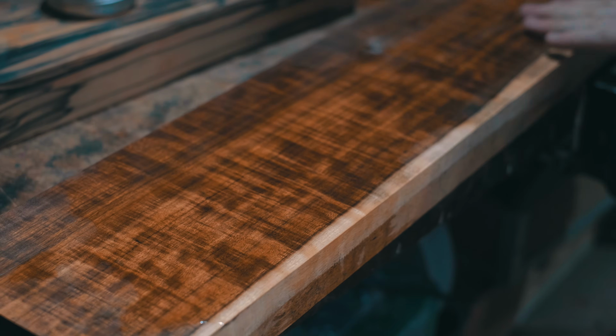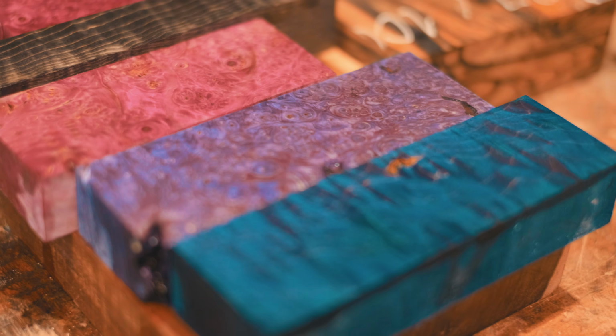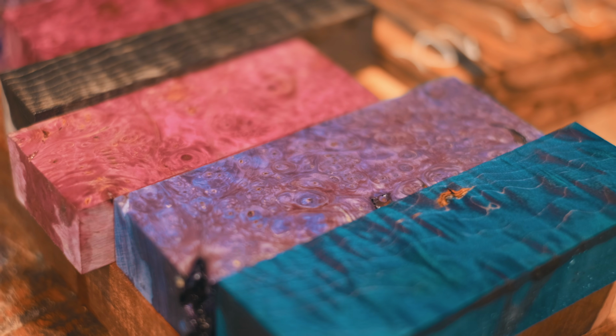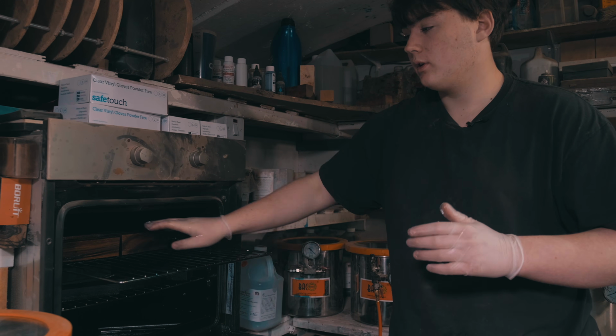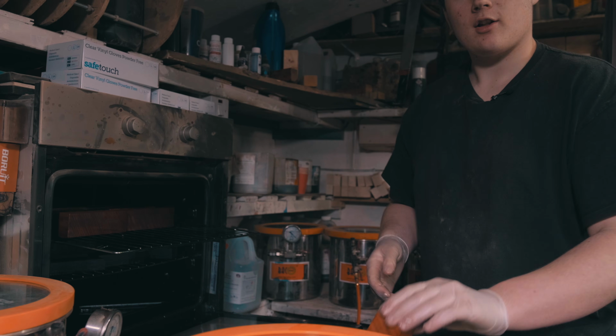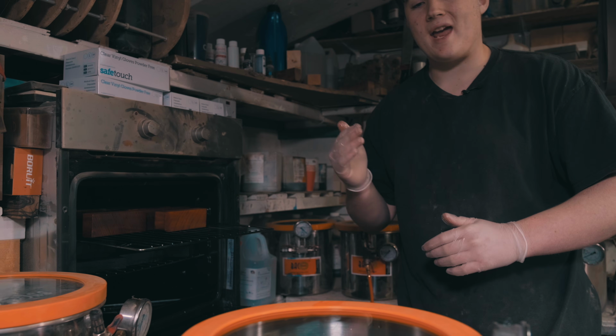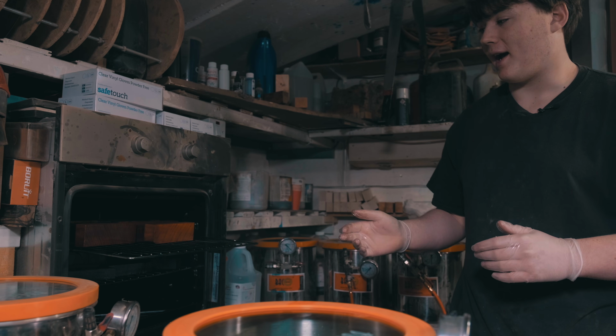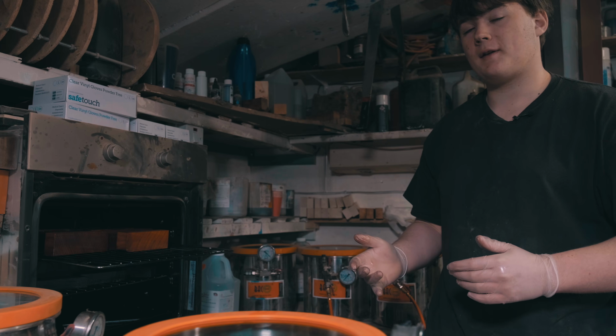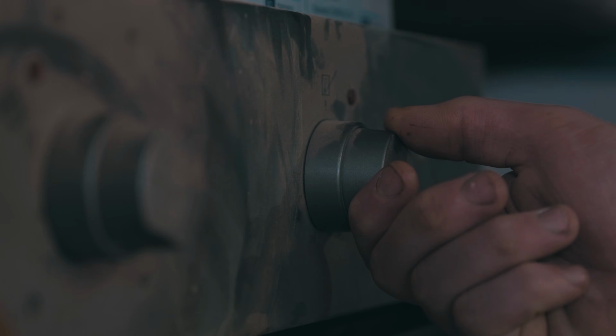The wood from the vacuum chambers goes into the oven at around 93 to 95 degrees C. You can go hotter than that, but you'll get excess bleed out, which is where the resin bleeds out of the wood, and you lose then density. But if it's too cool, it then won't cure, which again isn't good. If the oven starts off too cool and then heats up, that does have an impact, but the cure time will be about an extra 50% longer. So it's best to have the oven hot when you put them in to start that cure.